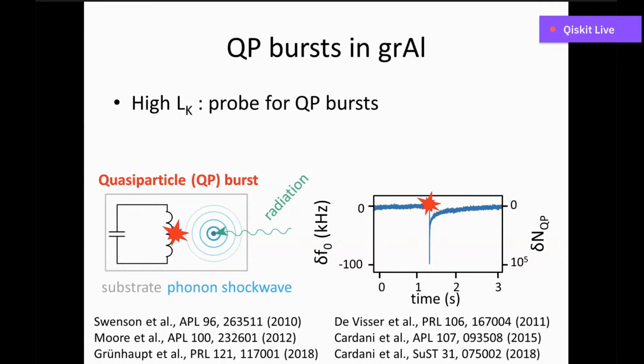And the burst will create a drop in frequency that is bigger as the kinetic inductance is bigger. So a high kinetic inductance material, or a material that can be made to have a high kinetic inductance, such as granular aluminum, will be a good choice to be a probe for the effect of radioactivity.